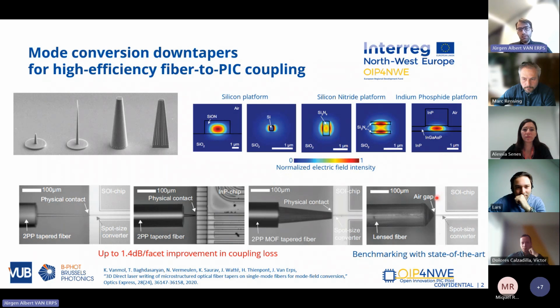So one way of reducing those connection losses is to use lensed fibers. This is a typical commercially available lensed fiber where a lens has been polished directly on top of the glass fiber. Then you position the fiber at a certain distance from the chip such that you have a small air gap between the two. If you are positioned in the focal point of the lens, then you will reduce the size of your mode field coming from the fiber and couple to the chip more efficiently.